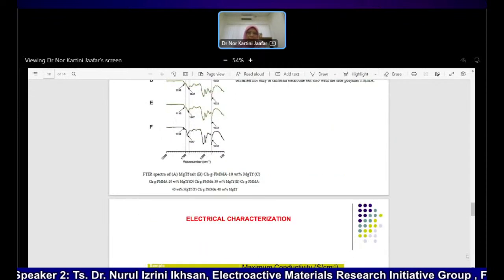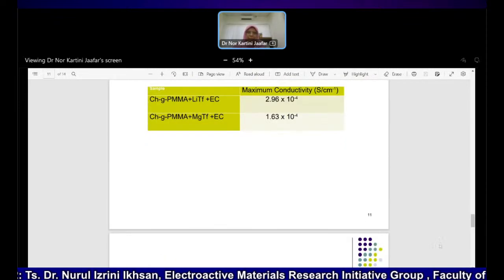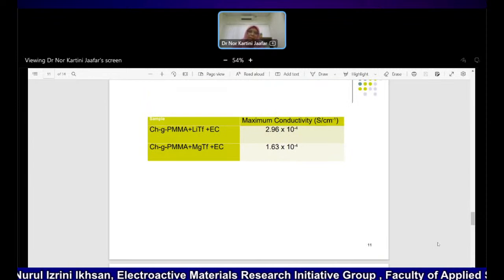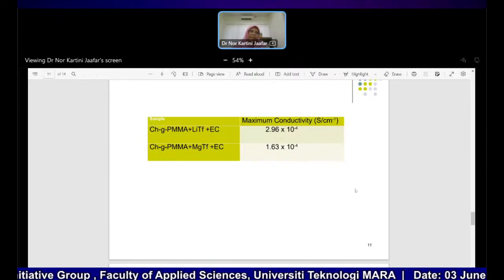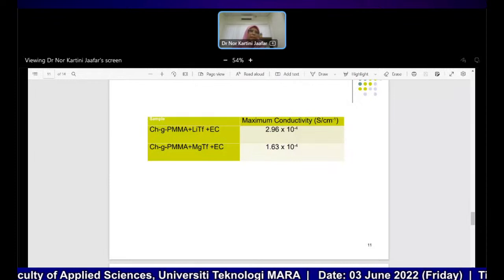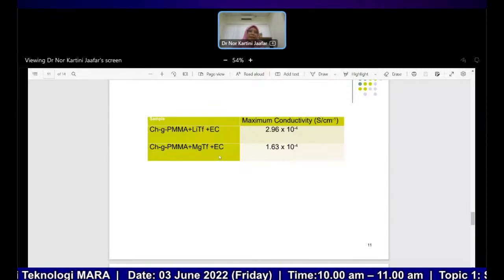Okay, and then we test the sample with EIS. Just to show here the value of conductivity that we get. The maximum conductivity value we get is to the power of -4. This shows that the grafted polymer will enhance the conductivity of the chitosan, and also with the help of plasticizer.